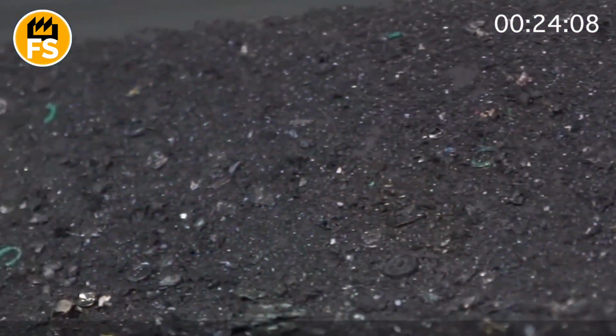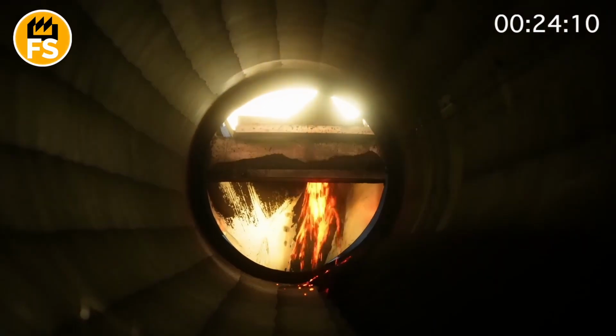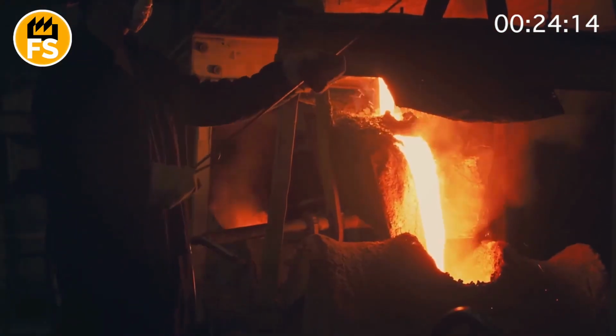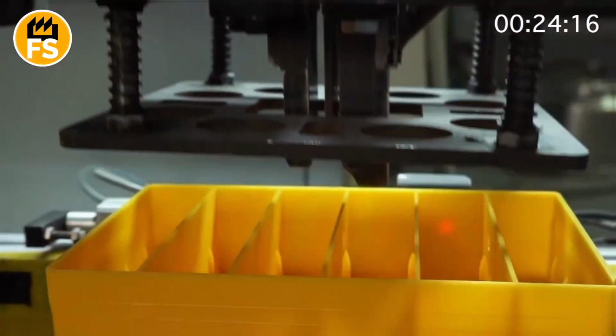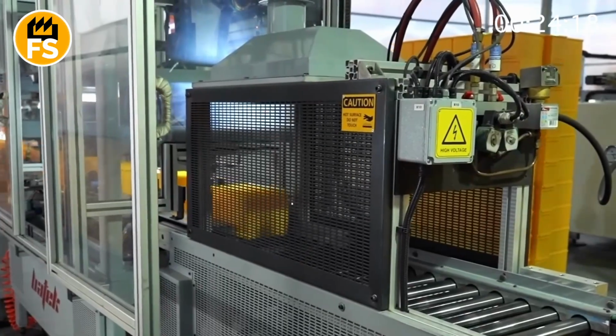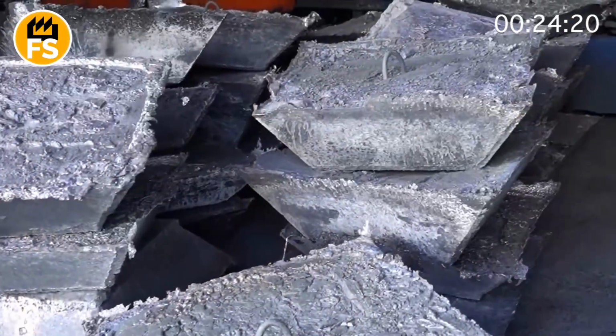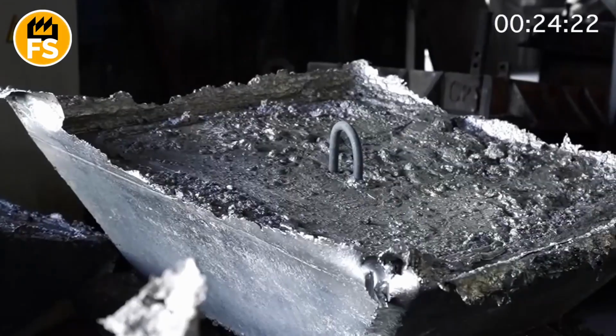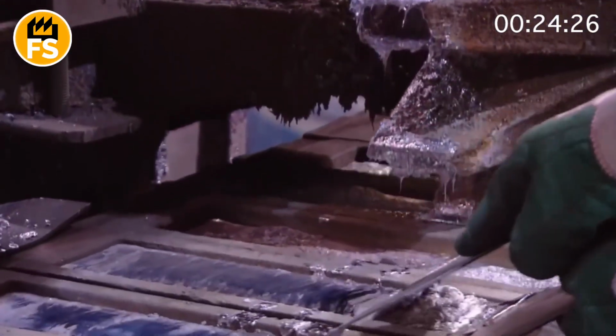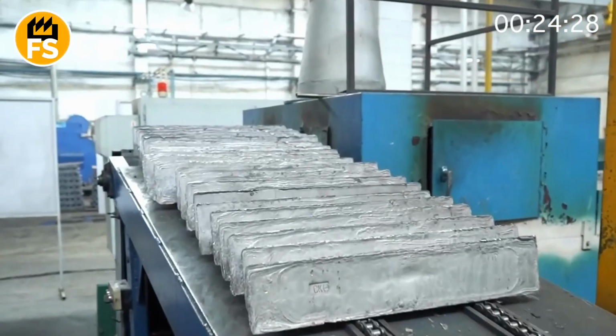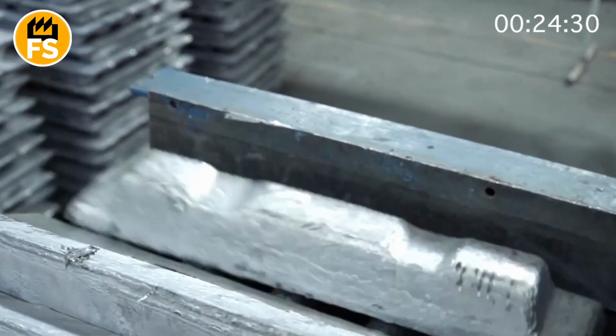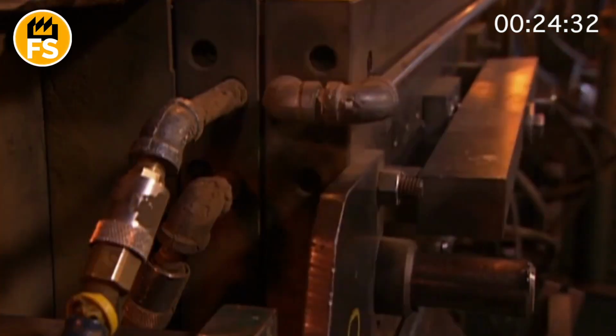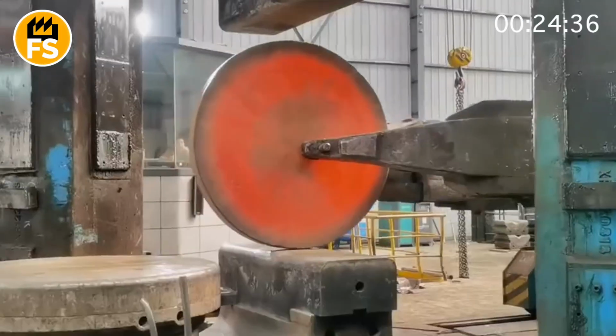For casting, however, special molds are made, usually from steel or cast iron. The molds must be very precise to ensure the correct geometry of the disc. The titanium is heated until it turns into a liquid. This is usually done in vacuum furnaces to prevent oxidation. The liquid titanium is poured into the prepared mold. After cooling, it solidifies, taking the shape of the disc. Casting allows for the production of discs with complex shapes that are difficult to achieve by forging.